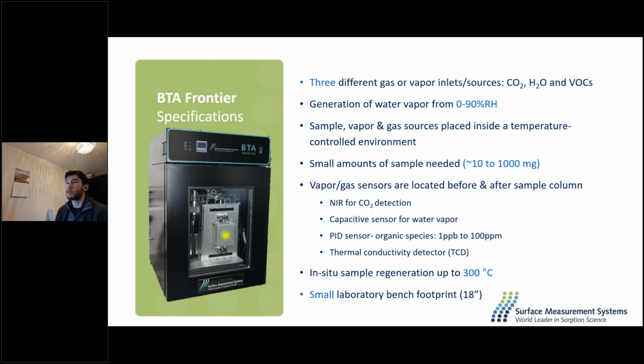It's a small column, so the whole system is adapted to very small amounts of sample. It's again a research instrument. It's 10 to 1,000 milligrams of sample, depending on the sample volume. And at the outlet, there are a suite of sensors that are tuned for particular gases and vapors. So there's a dedicated CO2 sensor, there's a dedicated water vapor sensor, there's a dedicated volatile organic compound sensor, so a PID sensor, as well as a thermal conductivity detector.